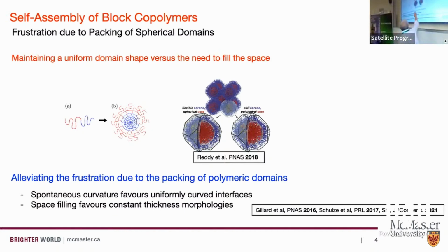And what that means is that now these spheres need to be stretched. And then you can have two scenarios. One is that you're going to stretch such that the micelles will be deformed to assume a shape which is different from sphere. And of course, they don't like it because that's not the natural state. That's going to cost you energy. But on the other hand, filling the space requires that.